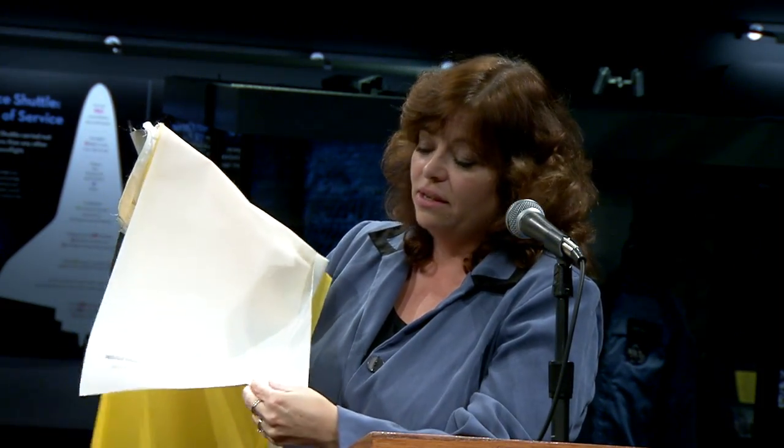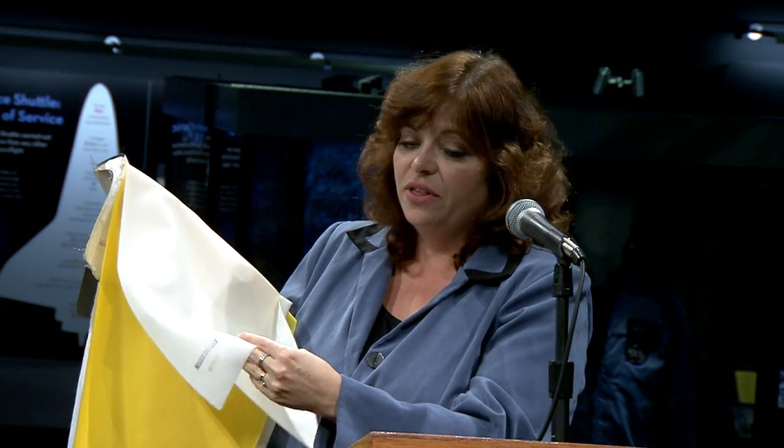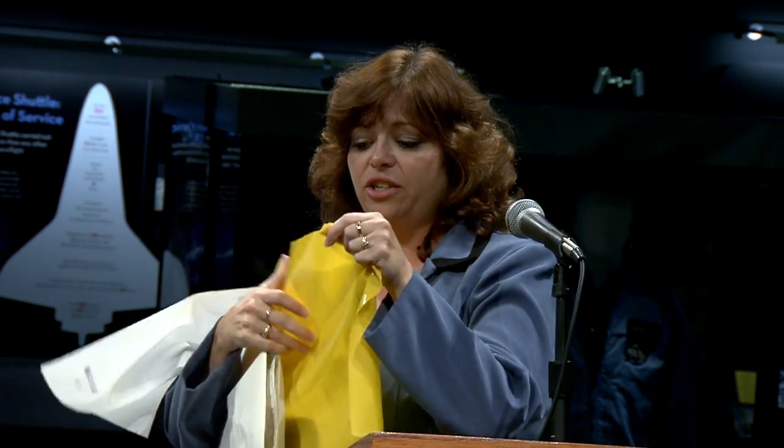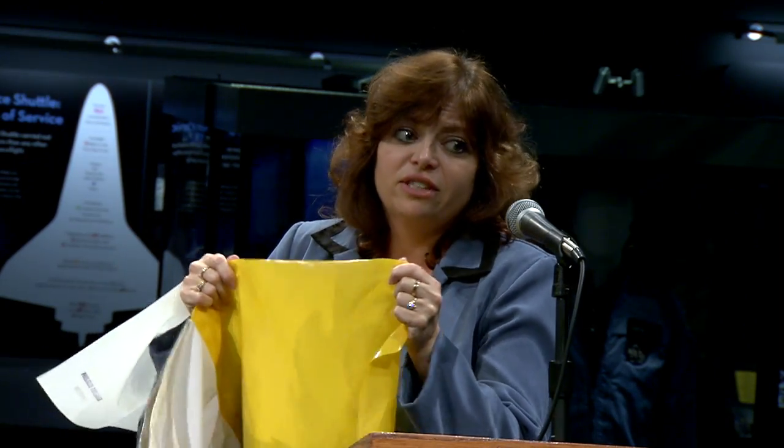we have this, it's called a restraint. It's made out of polyester. And this really gives the bladder its shape, helps hold the shape, and it takes all of the loads so that you're not putting this material in tension so that you have a chance of it ripping.